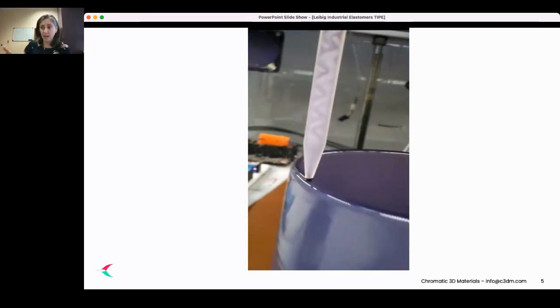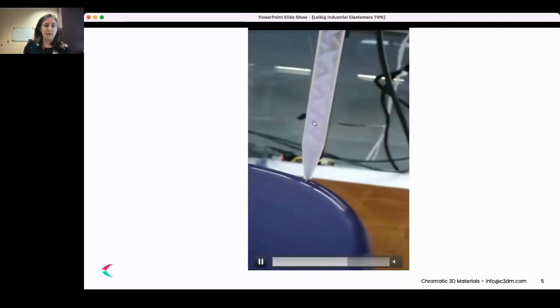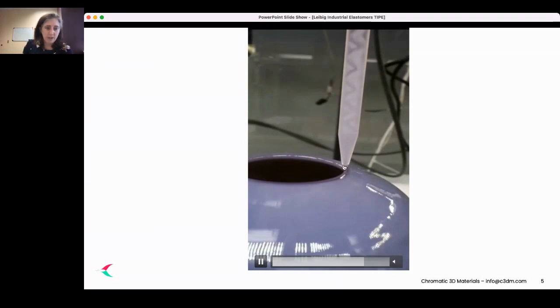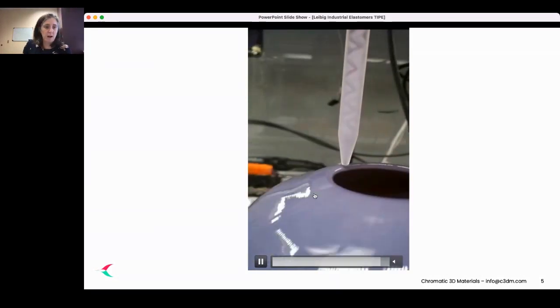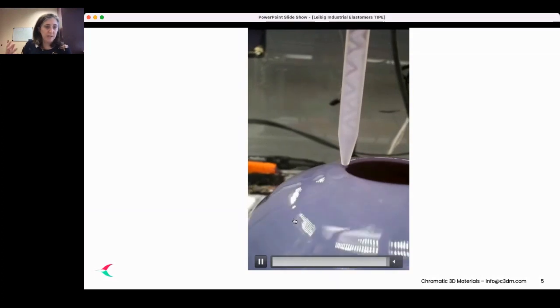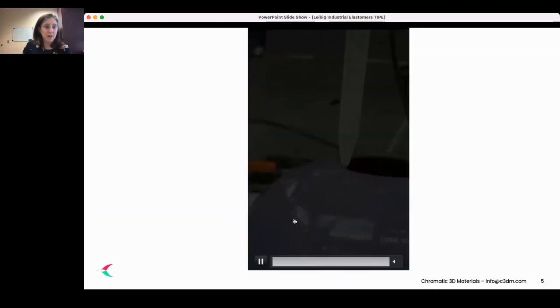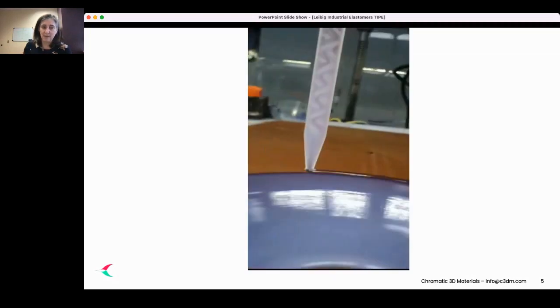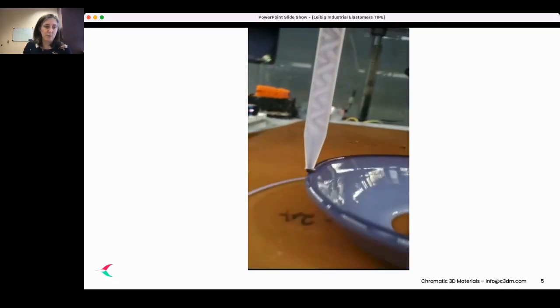And what's going on here during the print, when they start to come into contact in that mix head, they're starting to react, but then down, the material coming out is partially reacted, but then it really reacts very well with the material below and the substrate. So the result is that you get a part with isotropic properties, and that's really important. We don't see any print lines.